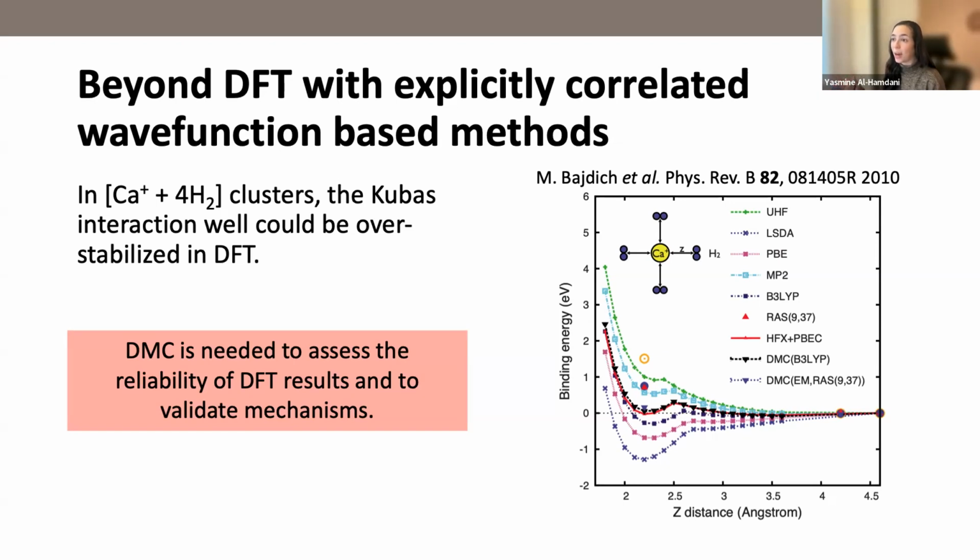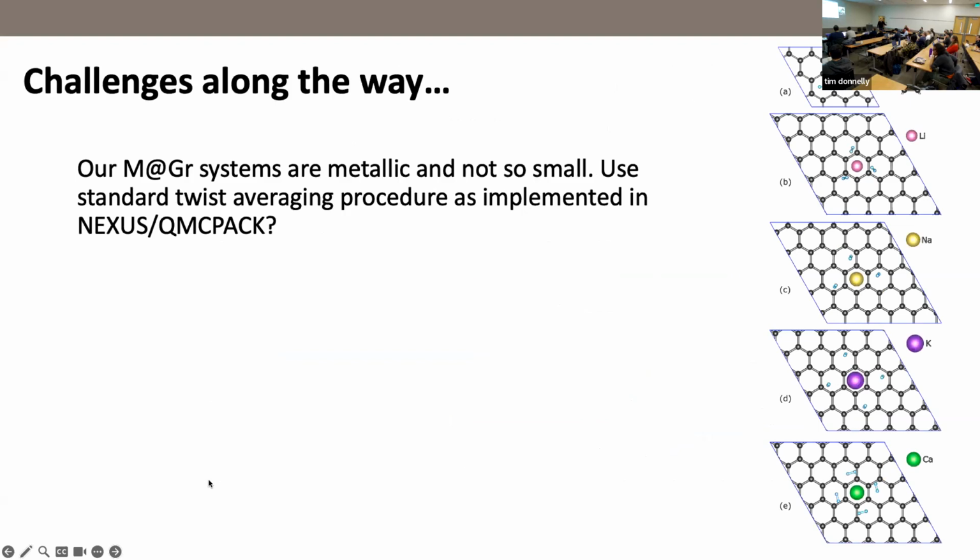There was agreement there. However, I think it would still be interesting to use quite a different approach, because for this kind of system I would expect that perhaps PBE plus LDA are too close together in what they predict in terms of orbitals. You saw that with PBE plus U, even with a high value of U, we would still get that state, so the orbital would still look pretty much the same. Then on the QMC side, you would expect that would not be affected so strongly. However, it would be interesting to use a completely different method, where maybe it would flip how the orbitals look. Thank you. Anyone else have a question?